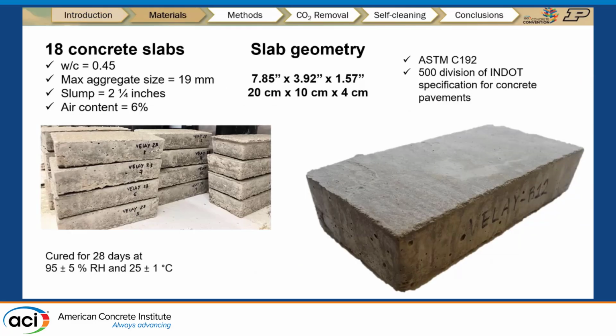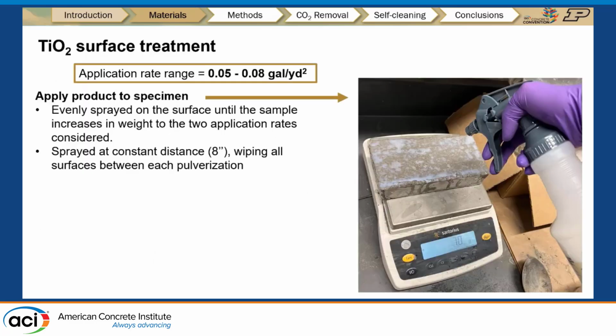We have cast 18 concrete samples according to the ASTM standard and the INDOT specifications for concrete pavement, and after that we cured them in the standard lab condition. For the titanium dioxide surface treatments, according to the manufacturer, the suggested application rate range is from 0.05 to 0.08 gallons per square yard. We have applied them at the minimum and the maximum application rate to see what happens